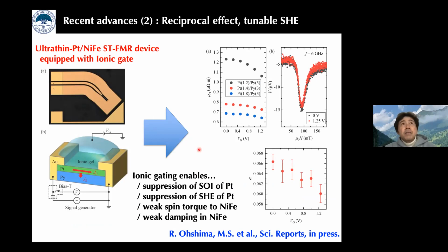And as I mentioned, we experimentally demonstrated gate tunable inverse spin Hall effect. And the spin Hall effect is a reciprocal effect of the inverse spin Hall effect. From the Onsager reciprocity, we can expect a successful tunable spin Hall effect, as in the case of the tunable inverse spin Hall effect. So to check our concept, we fabricated spin transfer torque devices, and ionic gel is once again equipped on top of the ultrathin platinum, and platinum is evaporated on top of permalloy. And we observed the gate change of the output DC voltages, and we observed the gate-dependent Gilbert damping constant of permalloy because the spin torque effect is suppressed.